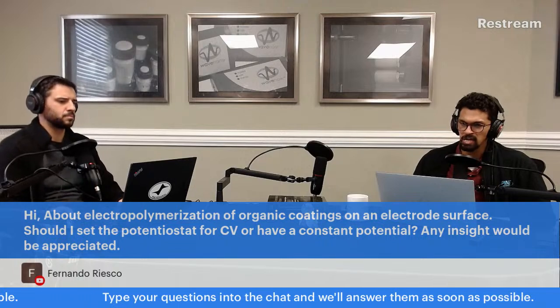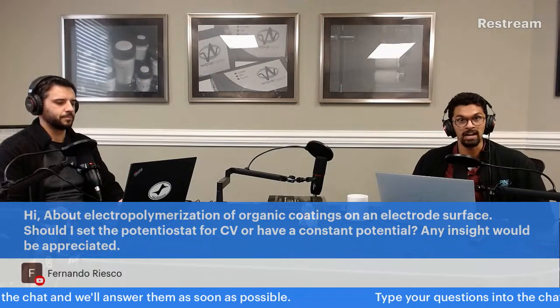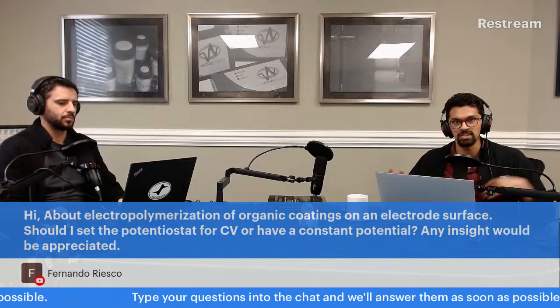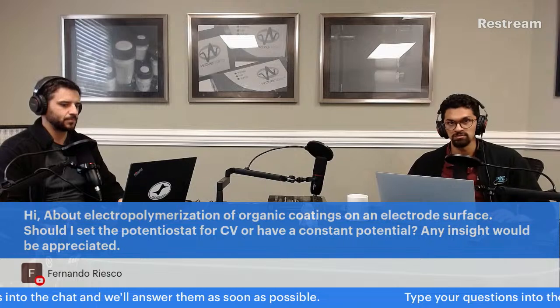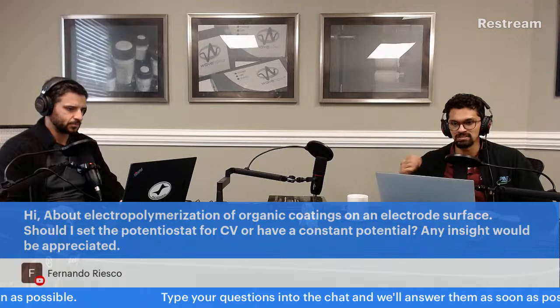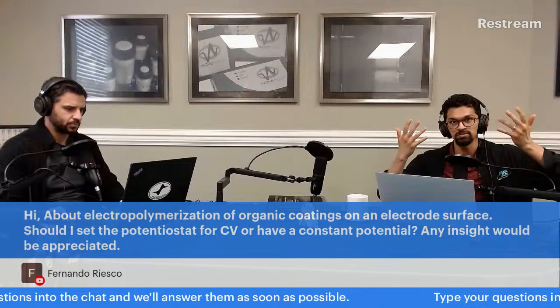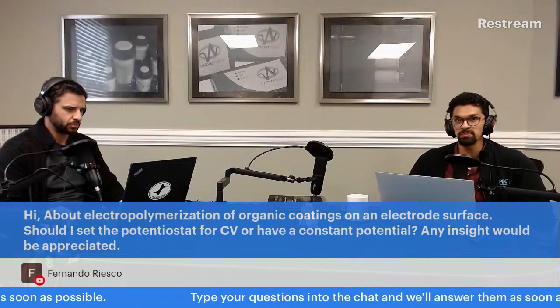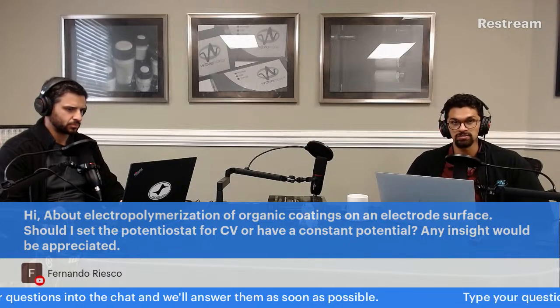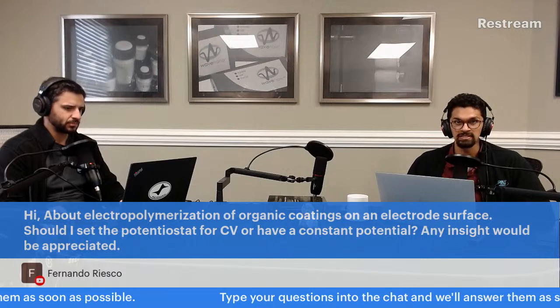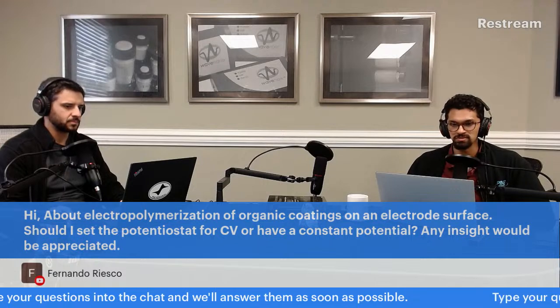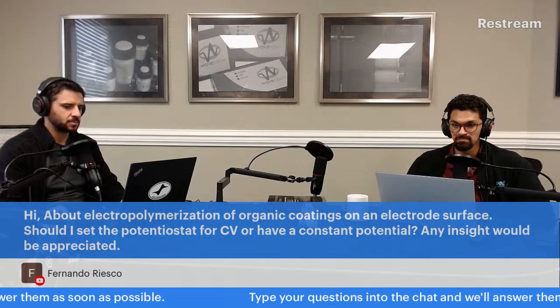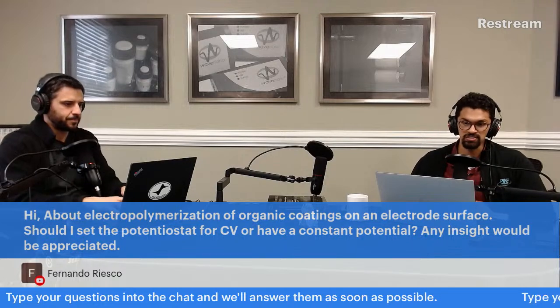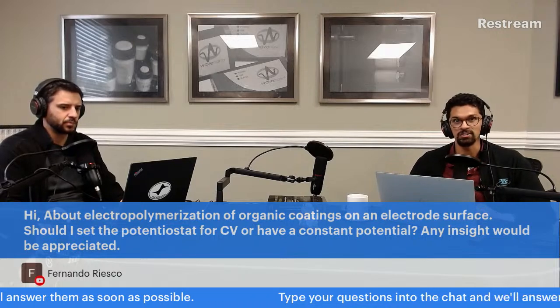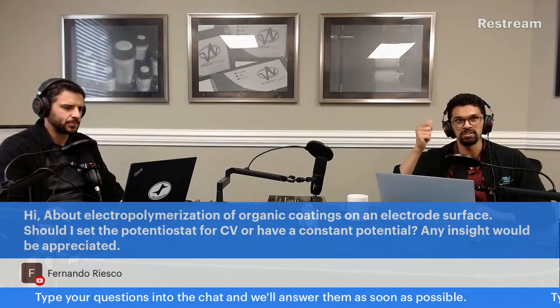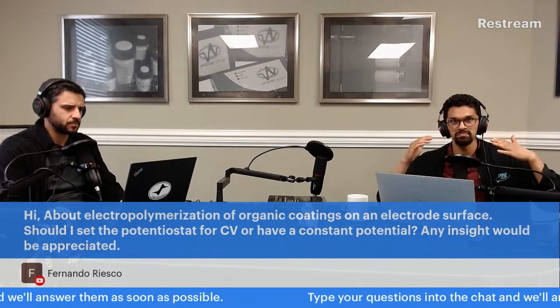Cyclic voltammetry is usually helpful when it comes to understanding at what potential reactions occur. So as you sweep the potential, initially I'm assuming you're having your organic molecules around, randomly diffusing, there will be a potential where you'll start to see either the oxidation or reduction reaction that allows the organic molecule to polymerize. But once it polymerizes on the electrode surface, my guess is that it's going to become a film on the surface, and it's not going to do very much. So if you were to set a constant potential, that actually might be useful because nothing's changing, and you'll probably see a sharp decrease in the current. Once the organic molecules polymerize, the current's going to fall off because it might be insulating.